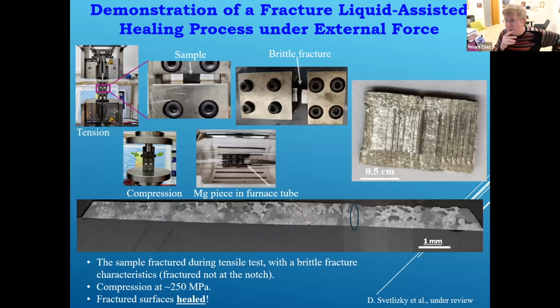This is without the shape memory alloy. Therefore, we had to apply external force, compressive force. Eventually, we hope that the shape memory alloy will give it intrinsically. And then if we do thermal treatment at relatively low temperatures that are sufficient to melt this core, it will be driven by capillary forces and fill the crack. And if you also have compressive stress that narrows the gap of the crack, you can easily fill it.